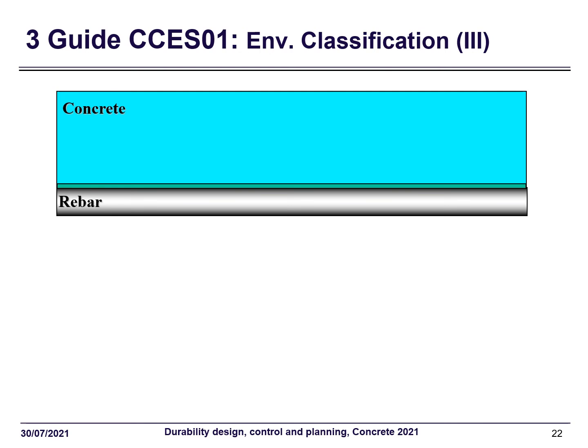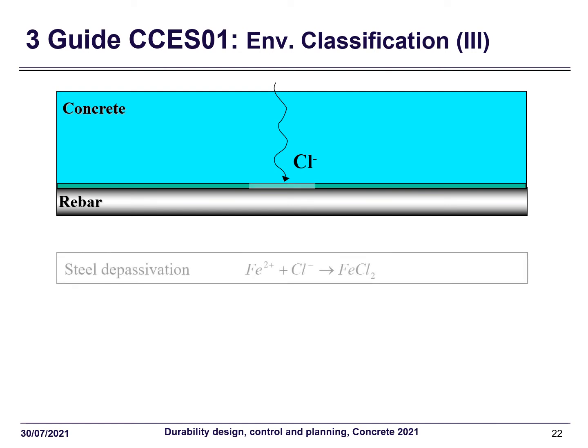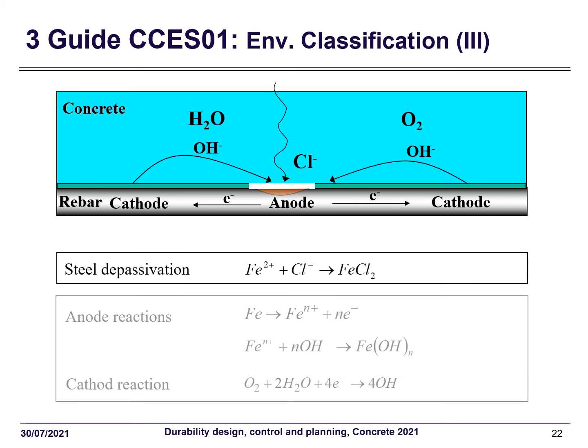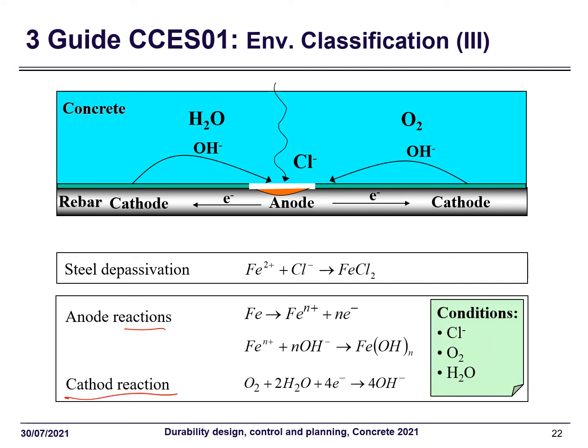We all know that in this environment, the risk comes from the chloride ingress to the surface of the steel bar, and then the steel will be depassivated, and we will have the electrochemical reaction of corrosion. That means we have the anode reaction and cathode reaction. To make it happen, we need some conditions. First is the chloride, sufficient concentration of chloride on the steel surface, and oxygen and water to make the cathode